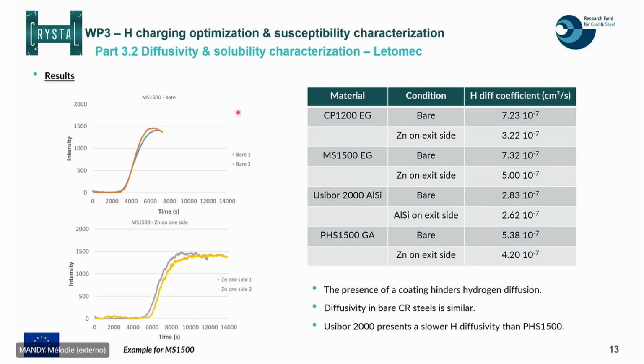Some words about the results. So typically results that you can obtain here, for instance, for the MS1500. They perform these tests on the bare steel and also on the zinc-coated material, or the aluzi-coated material for the Usibor 2000. In each case, the coating was only on one side of the material, just to see its effect. And you see a bit the typical experimental curve that you can obtain. In terms of results, what we see is mainly the diffusion coefficient of hydrogen that is summarized here in the table.